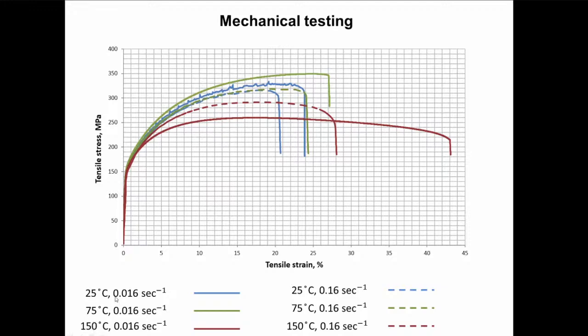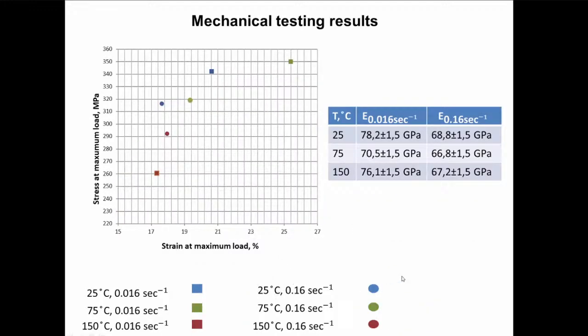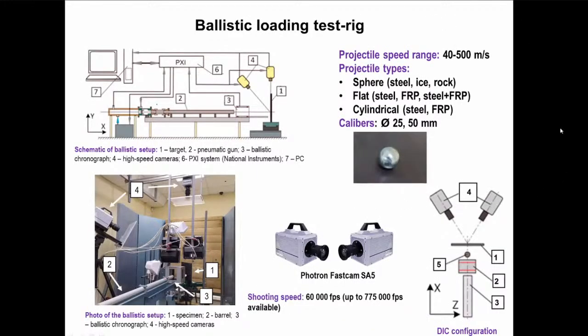So we obtained the stress and strain diagrams, and we evaluated the values of the maximum loads and the stresses and strains at the maximum loads for different loading speeds and conditions. As you can see, in comparison with the ambient conditions, when we raise the temperature to 75 Celsius, our maximum stresses and strains slightly increase, and then when we go to 150 Celsius, they decrease to some degree.